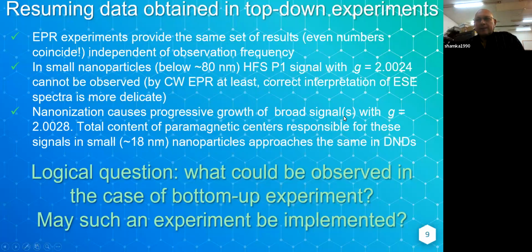Let me summarize. EPR experiments provide the same set of results, even numbers coincide, independent of observation frequency. It means that we observe the same things, and these things are quite fundamental. In small nanoparticles below 80 nanometers, the characteristic hyperfine-split P1 signal with this G factor cannot be observed, let's say more carefully, by continuous wave EPR at least, because for pulsed EPR the picture is not so clear. They do observe them, but for very specific reasons. I can explain it later or after the lecture, if someone is interested.